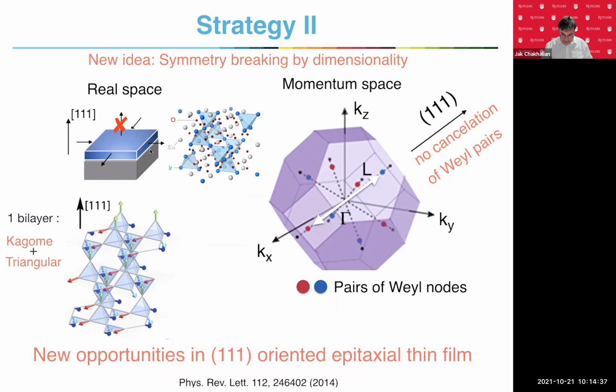This is the momentum space, the Weyl nodes. You will get a special pair of Weyl nodes along this direction, which will not cancel out, and it'll give you a very large response in your transport, in some exotic photonic response, and things like that. But you need to grow thin films to break the symmetry of the crystal. And I'll be brief here, and I'll tell you this is the huge problem. I'm just showing you the number of reports where people attempted to grow these films. Let me show you what's the real result and reality when they reported in wonderful magazines. But if you're an expert, I'll just show you the show and tell.